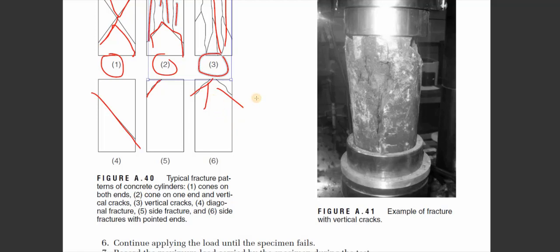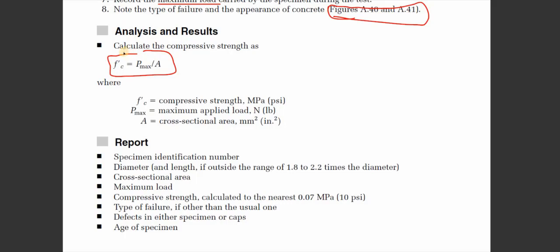This is the analysis and results. We calculate the compressive strength as f'c equals P maximum over A, where f'c is the compressive strength in megapascal, P maximum is the maximum applied load in Newton, and A is the cross-sectional area in square millimeters. At the end we report the specimen identification number, diameter, and length if outside the range of 1.8 to 2.2 times the diameter, cross-sectional area, maximum load, compressive strength calculated to the nearest 0.07 megapascal, type of failure if other than the usual one, defects in either specimen or caps, and age of the specimen. This concludes our experiment for today. Thank you.